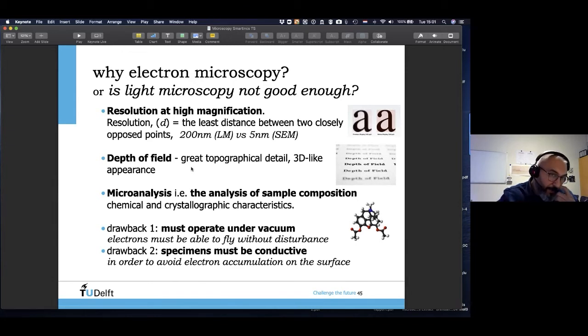There are new developments, of course, newer technologies where you can operate under relatively less vacuum, which is less detrimental for microstructures like cement paste, but still you need to operate under vacuum. Otherwise, your electrons cannot reach your specimens easily. They will bump into the water vapor molecules, and they will be scattered away, and that's something we don't want.